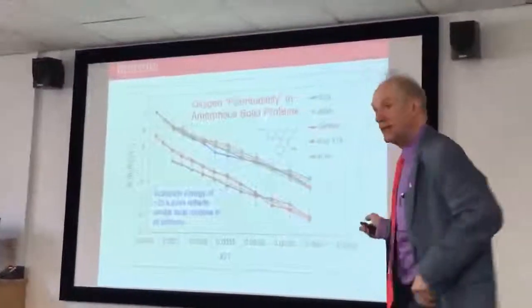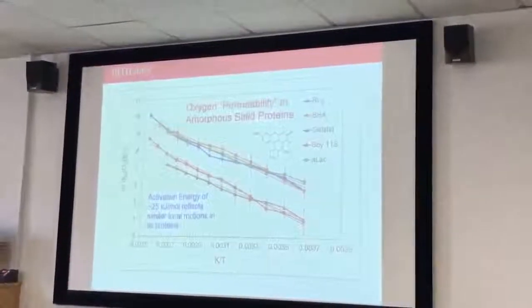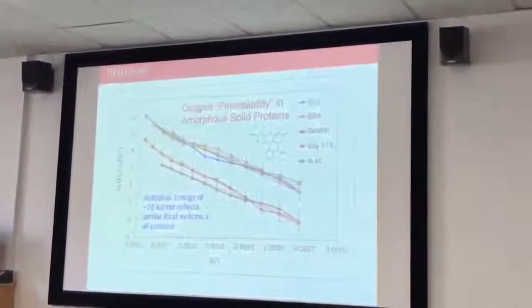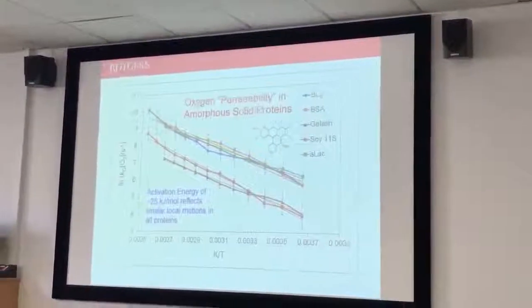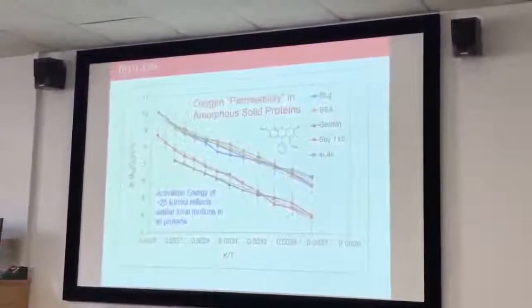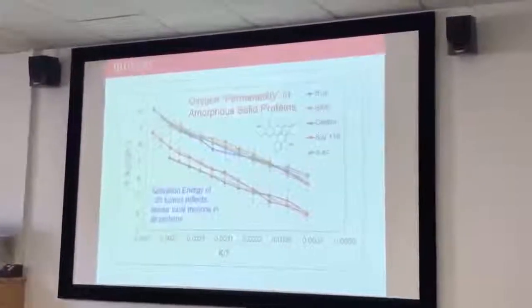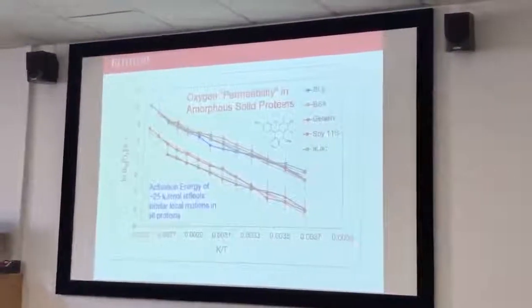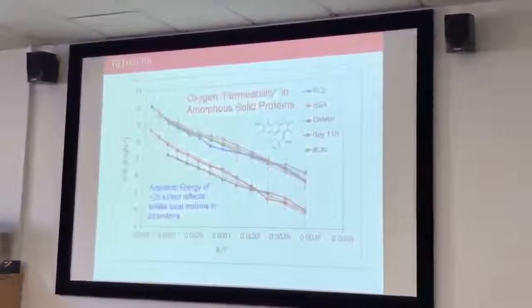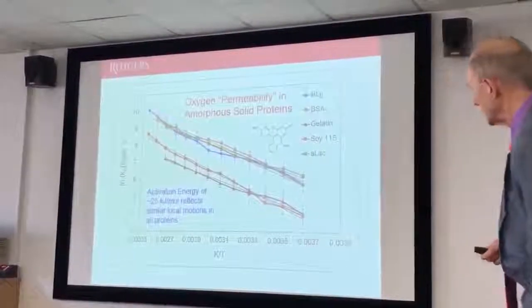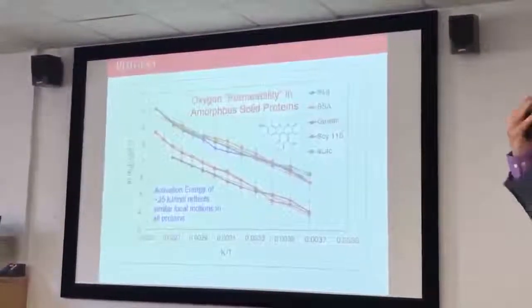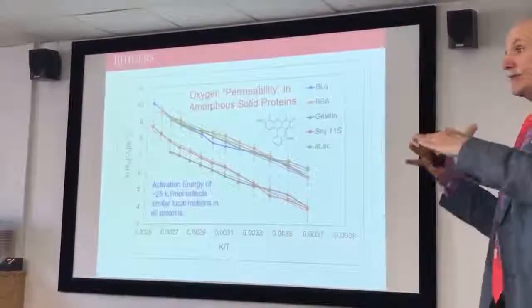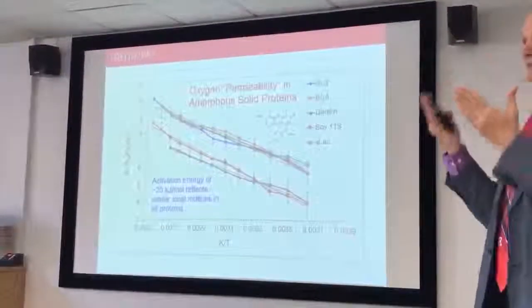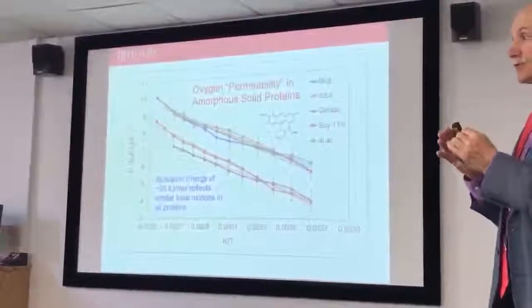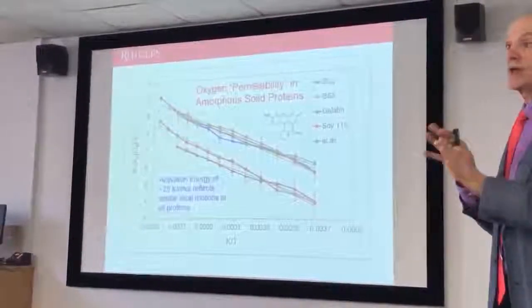We analyze for KQ, and we do the Arrhenius plot, and we get fairly interesting behavior, which is that in all five of the proteins, beta-lactoglobulin, BSA, gelatin, legumin globulin from soy, and alpha-lactalbumin, you get parallel curves, all giving an activation energy of about 25 kilojoules per mole, which indicates that whatever dynamics are facilitating oxygen movement through the matrix is approximately the same in all the proteins.